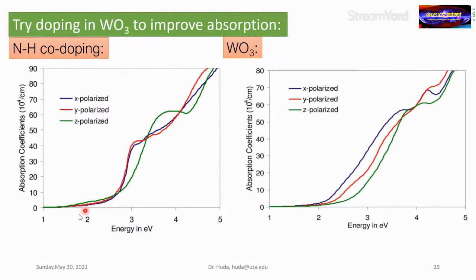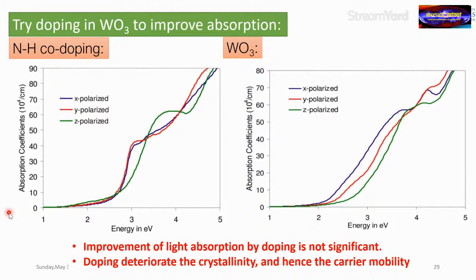Now, if we do that, this is the optical absorption, and this is the tungsten oxide without doping. Now, you can see that around 2 electron volt, the absorption probability increases slightly, not much. It's a very slight, small enhancement, but it did enhance. It is not good enough for, let's say, robust practical applications. So we now need to find a different methodology to increase this light absorption in tungsten oxide.